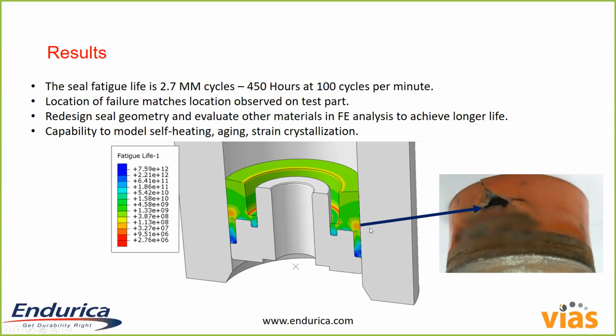What's more interesting is you can actually do design optimization. So you can imagine that the shape of the insert here has an effect on the stresses and strains that are experienced, and you can ask the question, what shape should that be to get as much life as we can? In this case, we predicted a life of about 450 hours, and this was an initial model.